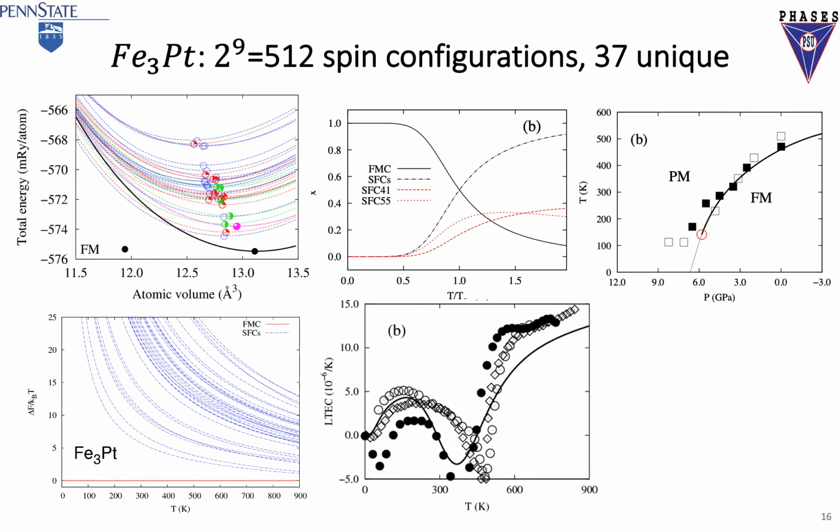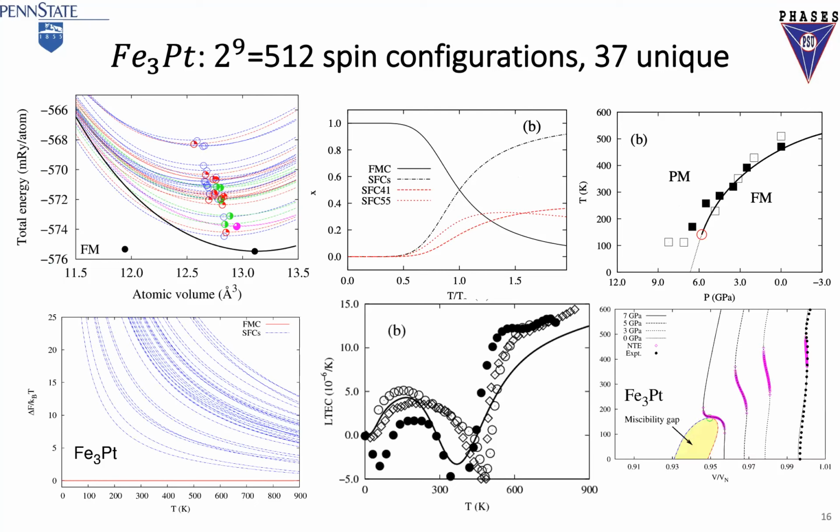All right, so we did magnetic calculations, and I don't have time to go through all of them, but just to show you a flavor. We predict the transition temperature as good as experimental measurements. That's one system. We did another, and even more important, we predict negative thermal expansion in this temperature range and pressure range. So negative thermal expansion or negative thermal expansion effect is not intrinsic to the lattice. It's a mixture of different states that compete with each other. It's a competition between different configurations. It's not intrinsic. Of course, if they compete together, you can measure its softening modes.